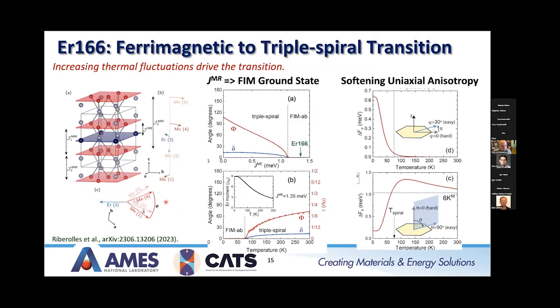So the magnetic structure, it turns out we can model it as being in what we're calling a triple spiral order. This is the structure between T-spiral and TN. It's quite similar to the double spiral that's found for yttrium manganese 6 tin 6. But in our case, of course, we have a magnetic erbium ion, and this also participates.